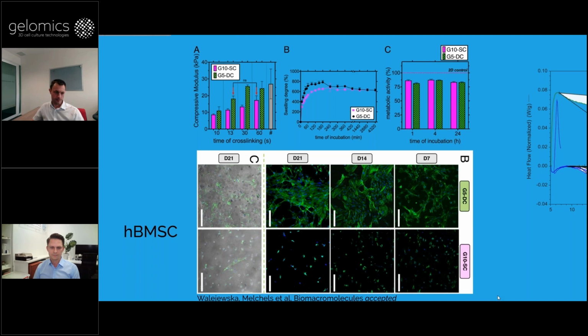So these cells are human bone marrow-derived stem cells. The top ones are in the double cross-linked gel, and the bottom ones in the directly cross-linked, single cross-linked chemical gel of the same stiffness. So really, our hypothesis was that people tend to focus on stiffness, and yes, stiffness is very important, but it's definitely not the only thing, because these two gels are the same composition and the same stiffness. So the microarchitecture definitely has a very big effect as well.